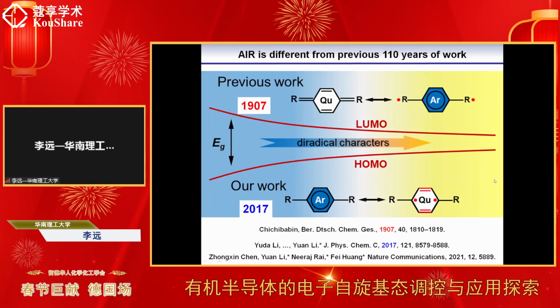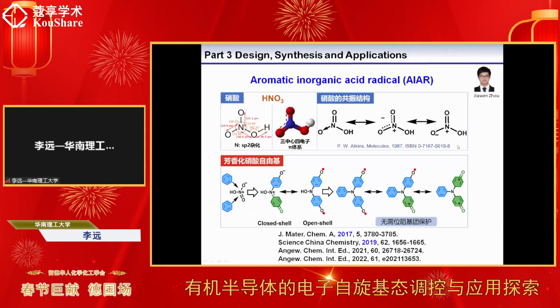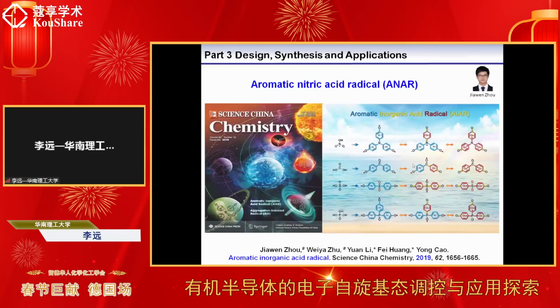And in the third part, I will show you some other aggregation-induced radical systems, for example, the aromatic inorganic acid radical. This is the aromatic nitric acid radical. This is the resonance structure, and we found this type of radical showed very high stability in air, and also very high stability in electrochemical tests. Then we also proposed the aromatic inorganic acid radical can be applied to other inorganic acids. We are trying to synthesize all of these kinds of radicals, and we found that they showed very interesting properties and high stability in air.